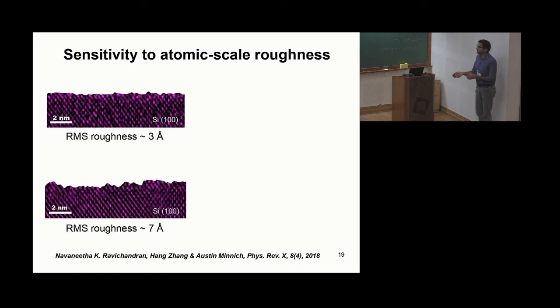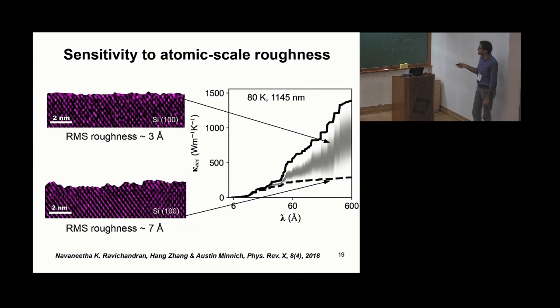And because such phonon-specific information is available, we went one step further and tailored the surfaces of the membranes to different roughnesses. These are two different high-resolution TEM images of two different silicon membranes, and we observed drastically different accumulation functions, precisely because the phonon scattering mechanisms in these membranes were very different. So in a smoother membrane you get higher thermal conductivity, and in the rougher membrane you get lower thermal conductivity.